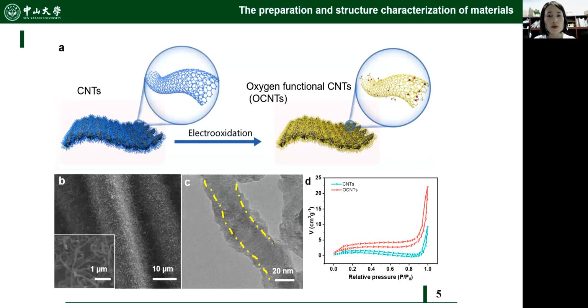In this work, we grow 3D carbon nanotubes onto the carbon cloth surface through a chemical vapor deposition method, and oxygen is further introduced through a one-step electrochemical oxidation method. SEM images show that CNTs form a crisscross network on the surface of carbon cloth, and their morphology is basically kept after electrochemical activation. More elaborate microstructures of CNTs and OCNTs are further analyzed by TEM.